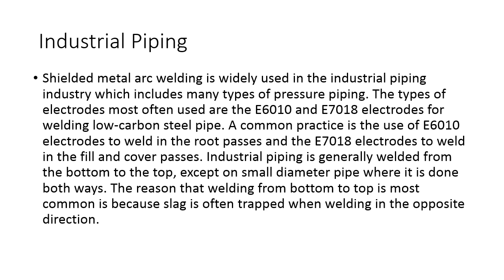This is done for a lot of different reasons, but E6010 is a fast freeze electrode and runs in a root very well. E7018 is a low hydrogen electrode, so then you can weld it out from there, and you're probably not going to have any issues with hydrogen-related cracking and whatnot if you'd have done it with all cellulose rods like an E6010. Plus, you get higher deposition rates with the 7018.